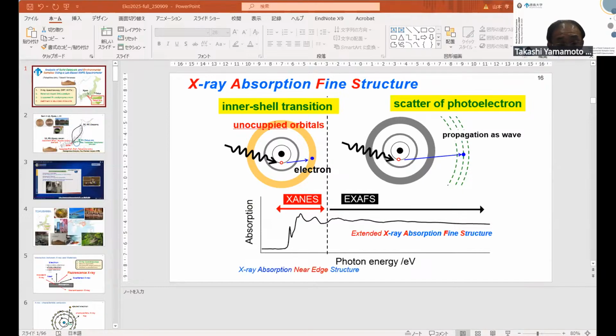Then around several hundred electron volts, small but fine structures exist. This is the same spectrum, but a different phenomenon occurs. This is a wide range, and this region is called EXAFS, extended X-ray absorption fine structure. This is a different phenomenon. When an electron is ejected, it propagates as a wave like this. If another element exists and backscatters, then the propagating wave and the backscattered wave interfere, and the absorption coefficient changes.